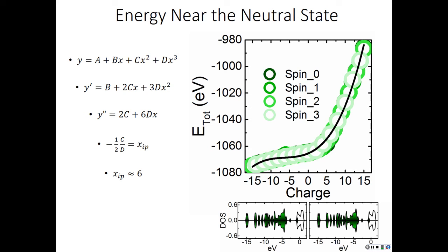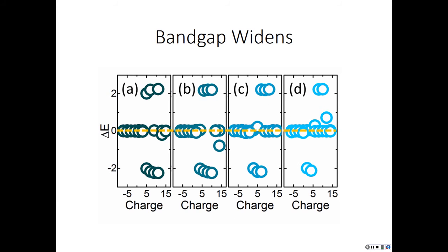But looking at these models, we then explored the band gap for these ones, which is here. I didn't mention that we looked at different spins of 0, 1, 2, and 3. And then we looked at the band gap for all these different oxidation states. For high oxidation states, from about 3 to 10 in these models, we can see that the band gap considerably widened to about 2 eV. Since we did this for both alpha and beta electrons, we multiplied the band gap of the beta electrons by -1, so that's why we have a negative band gap here.